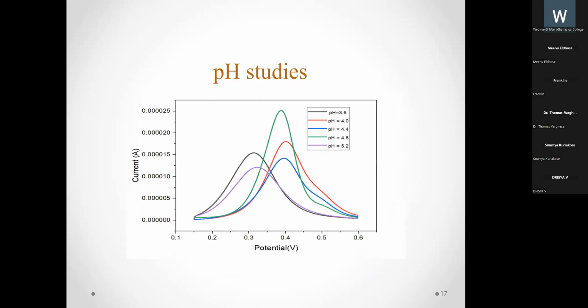Before moving on to DPV studies, it is necessary to fix the pH of that particular solution for getting the maximum peak height. So the pH studies were also done using the DPV technique. From this profile, it is clear that pH 4.8 has a maximum current. So we have fixed pH as 4.8 for the upcoming studies.